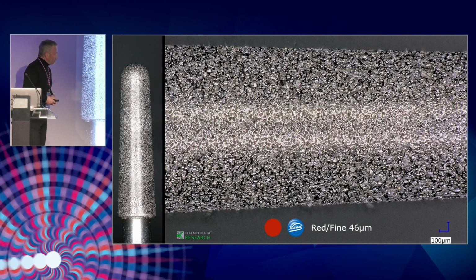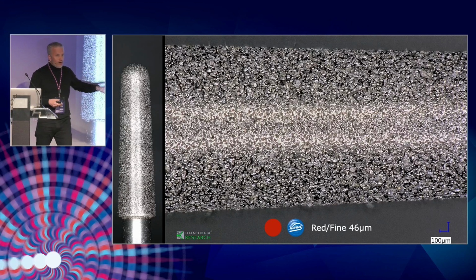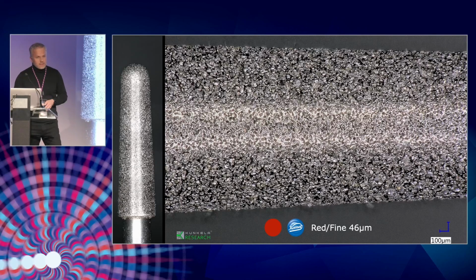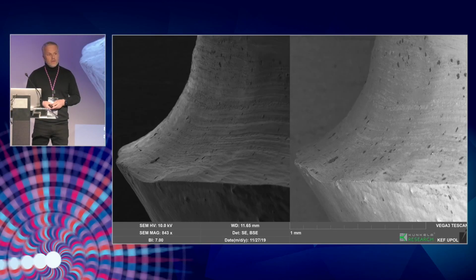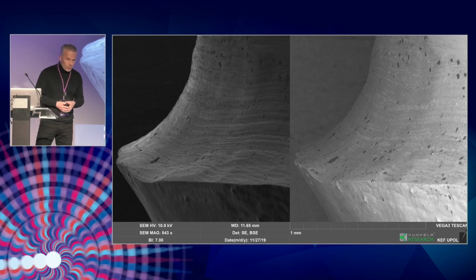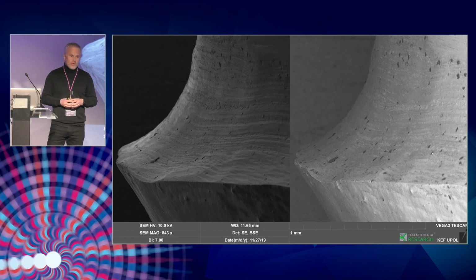And this is how the red fine instrument, with a 46 micron particle size, looks, and this is how the marginal edge looks. You can see the huge difference which can be influenced by the dentist. A lot of dentists, for example, start with the green stripe instrument and then try to smooth with the red one, but maybe we remove the marginal chipping, sorry, but we only seal these internal cracks inside.